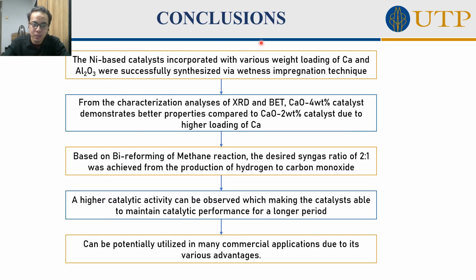So as for conclusion, the nickel-based catalyst incorporated with various weight loading of Ca and alumina were successfully synthesized via wetness impregnation technique. So from the characterization analysis, which is XRD and also BET, CaO 4% catalyst demonstrates better properties compared to CaO 2% catalyst, such as the pore volume and also surface area, due to higher loading of Ca. And based on the bi-reforming of methane reaction, the desired syngas ratio of 2:1 was achieved from the production of hydrogen to carbon monoxide, as I've explained in the result discussion just now.